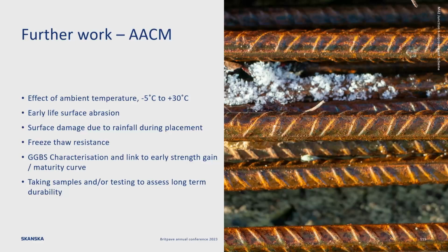If you take a continuously reinforced concrete pavement made from an AACM, an alkali activated cementitious concrete that incorporates calcined clay, reinforced with a continuous basalt fibre reinforcement bar, which is then surfaced with a thin surface of asphalt. And this is where we're looking now at our next trial: we're working with a company called Low Carbon Materials that is looking to introduce a low percentage of a carbon negative aggregate into an asphalt mix. The carbon negative aggregate, in proportions of about 10%, offsets the carbon in the rest of the asphalt to make it a carbon neutral solution. If you put a thin surface asphalt over a low carbon basalt fibre reinforced concrete pavement, clients should responsibly be all over that.